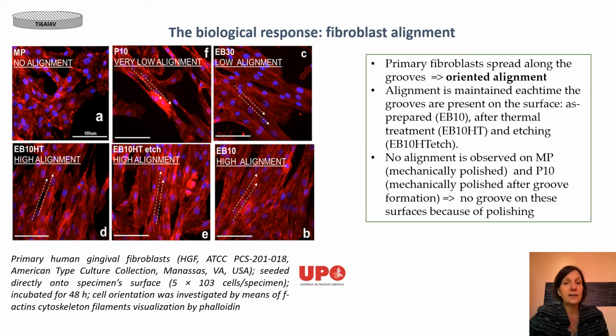You can see here the contact guidance effect. So every time you have these grooves on the surface, you have a high alignment of the fibroblast. If you have just the polished surface without any groove, you have no alignment. And if you treat the surface with the E-beam or laser and then you polish the surface, you reduce again the alignment because you are removing the grooves. So the alignment is strictly related to the presence of the grooves. And there is also an effect on the dimension of the groove. The better result is with grooves wide around 10 microns. If you have larger grooves, the effect is lower.